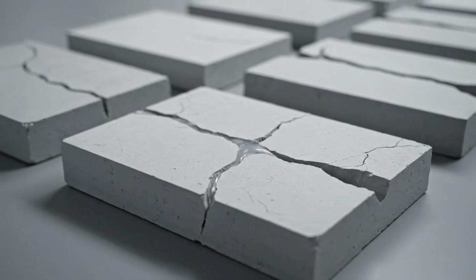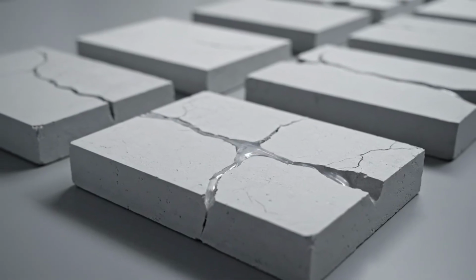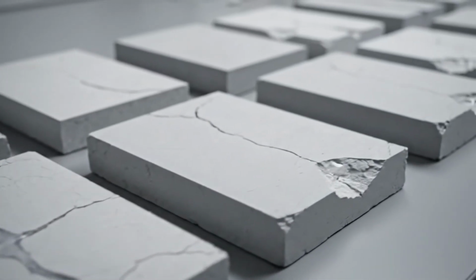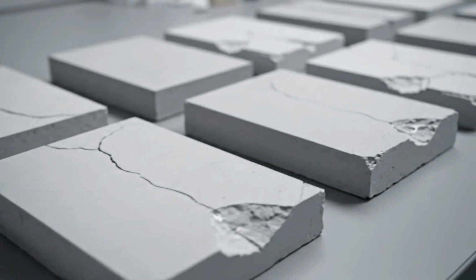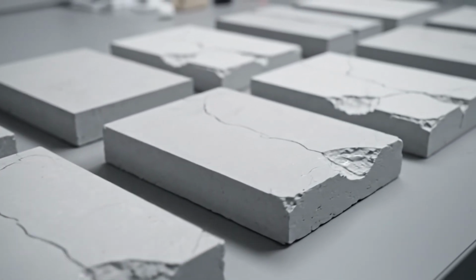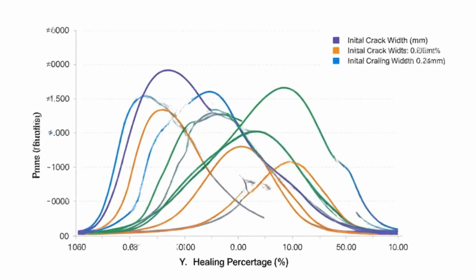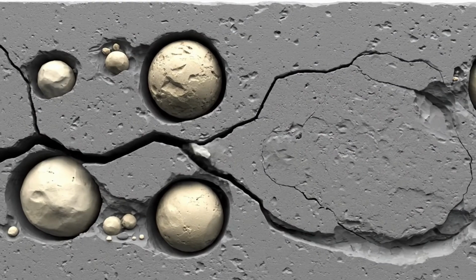They repeated the experiment with different crack sizes. Small cracks of 0.3 millimeters healed completely in 21 days. Larger 0.7 millimeter cracks healed partially in 60 days. The pattern was clear. The larger the crack, the more lime clasts it intersected, the more healing material available.